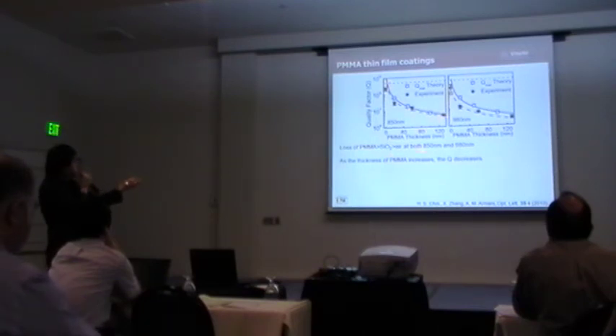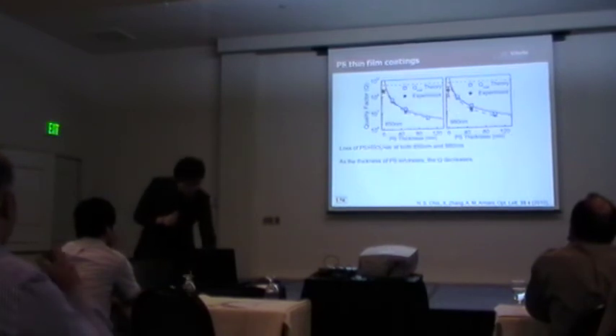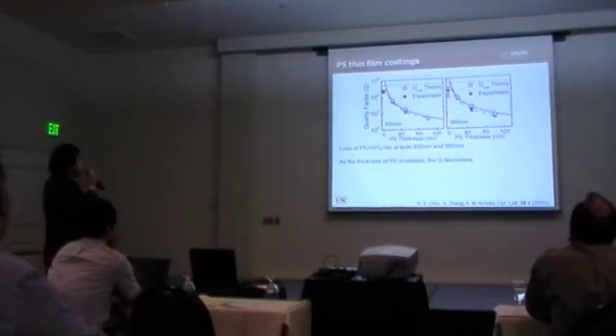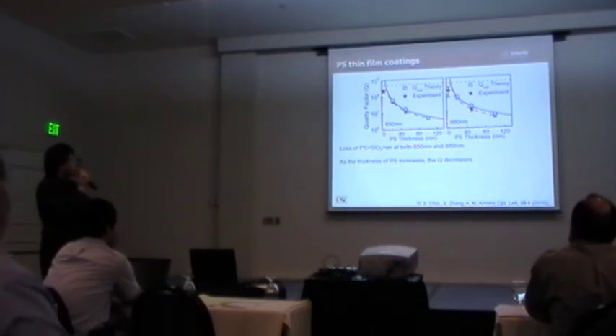This slide shows a comparison of measured and calculated quality factor as a function of PMMA thickness for PMMA hybrid devices. As you can see, there is good alignment between theory and experiment. As the thickness of PMMA increases, the quality factor decreases at both wavelengths because the loss of PMMA is higher than silica and air. This slide shows the same comparison as a function of polystyrene thickness for polystyrene hybrid devices. Again, there is good alignment between theory and experiment. As the thickness of PS increases, the quality factor decreases at both wavelengths, because the loss of polystyrene is higher than air.